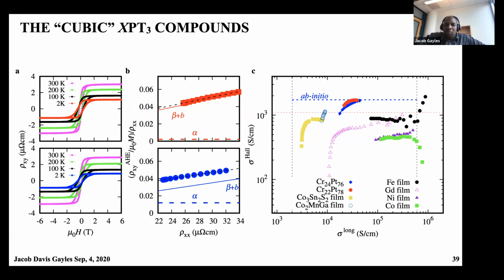I would suspect not greatly. I mean, comparatively for the Co2MnGa, we see a very large thickness dependence for the anomalous Hall. But this seems already at 60 nanometers to be quite sufficient to reproduce the theory.